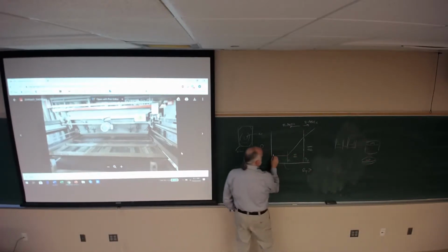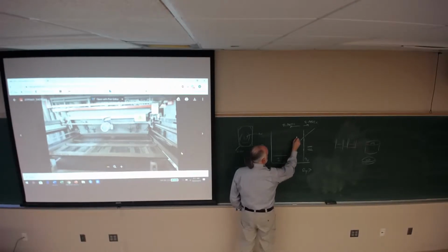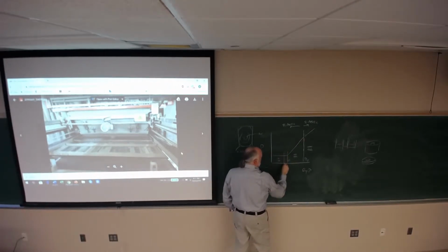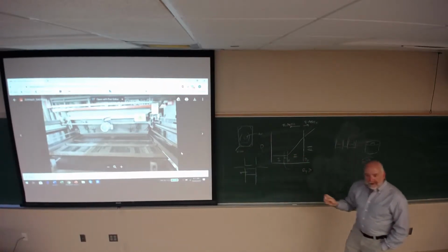They come in like this. And he sees that his onset of granular deformation decreased, and he gets a higher density in the presence of shear. Does that make sense?